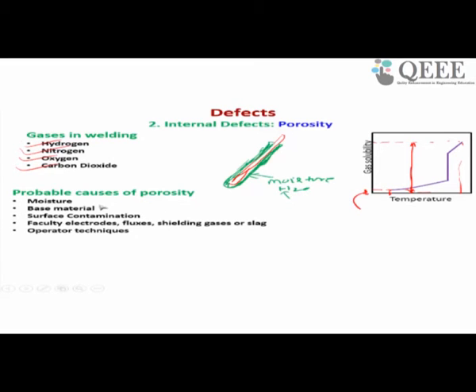Generally, as we discussed, porosity forms because of the presence of atmospheric gases, hydrogen, nitrogen, oxygen, carbon dioxide, which are available in the atmosphere. These gases have high solubility at high temperature and low solubility at low temperature. During joining, at the interface region we get a molten state, and since it is molten, there is a high chance that these atmospheric gases may be entrapped inside the molten pool. Then when the joint solidifies, the temperature becomes very low, and the solubility of gas is very low. As a result, it will try to escape from the molten pool, and you get porosity. That is the origin of porosity.